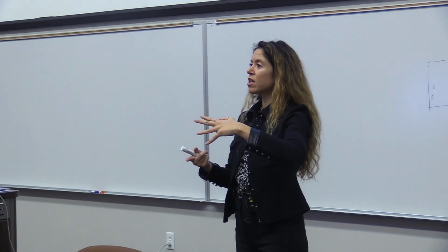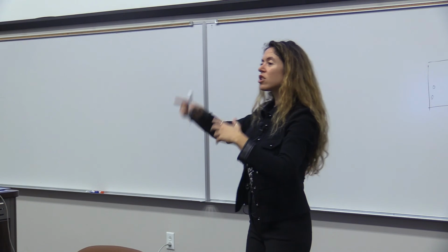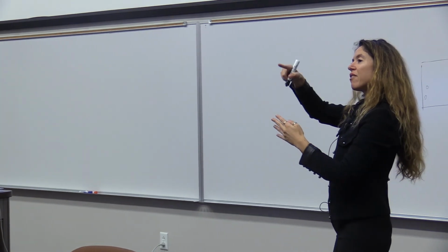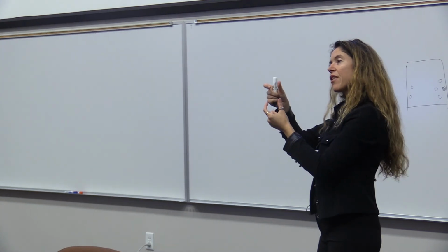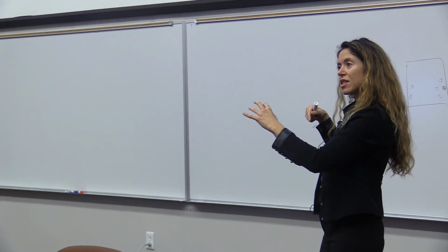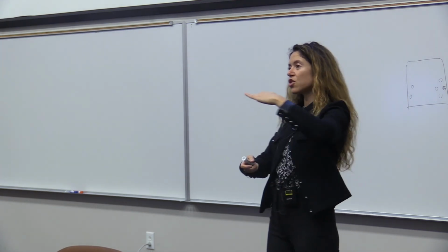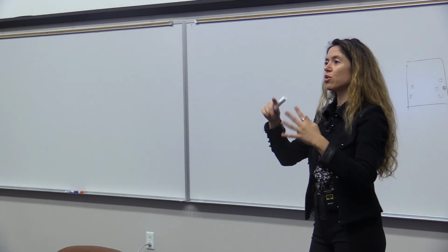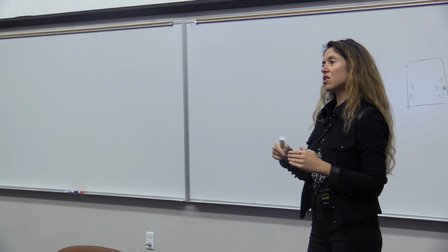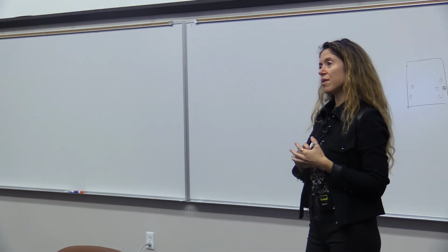To the period. Yes, it has to do with it because you don't want to drive the system too much out of equilibrium, because then the stress won't have any sinusoidal behavior at all. And you want to study this phase lag between the sinusoidals, as we said, right? Because the sinusoidal deformation and the stress following a sinusoidal, but it becomes out of phase. If you do it too fast, you won't see any fit to a sinusoidal for the stress. So the experiment won't work.